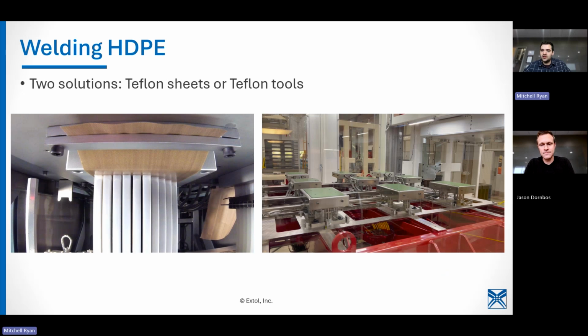Yeah. Yep. There was a great question from Sven about coatings that we can use, surface coatings, PTFE, chrome. I'll focus in specifically on welding HDPE, and our typical approach to that. It's actually a common hot plate welding material that we use. And we have two different approaches for that. We either use the Teflon coated tools, that's what you can see here in green along the right side. But for certain materials, either the customer doesn't want to deal with recoating those tools, or it's a lower volume, or there are additives in the HDPE that mean the Teflon coated tools won't even work.